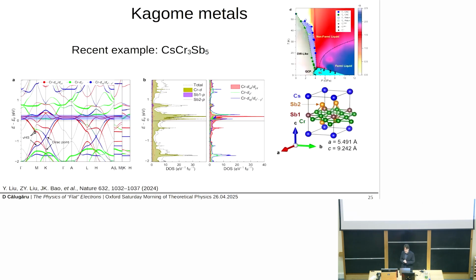At this point, you might be asking yourself, well, okay, this is all interesting, but is it really useful for anything? And the answer is, of course, affirmative. I'm highlighting here a very recent paper from last year, where they synthesized one of these Kagome metals. So even though this is a 3D material, it has many active orbitals, it has chromium atoms, cesium atoms, antimony p orbitals, you can still see here on the right-hand side a clear Kagome lattice, and if you squint at the band structure here, you can sort of see near the Fermi level, you have a flat band.